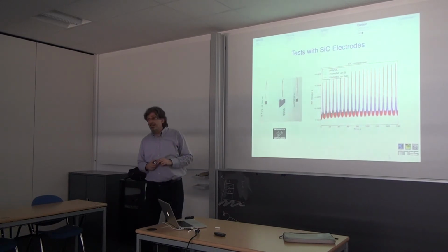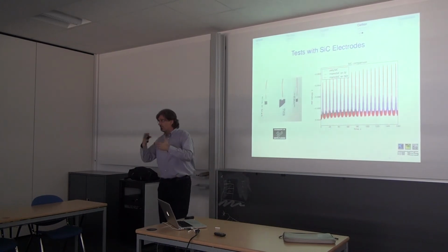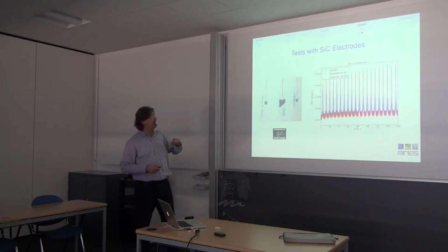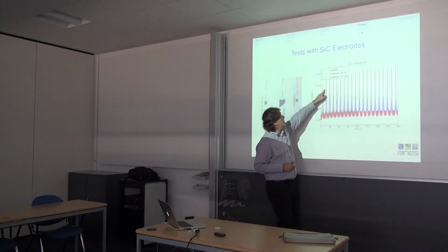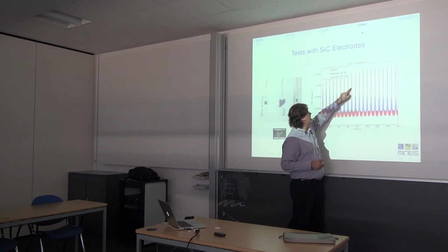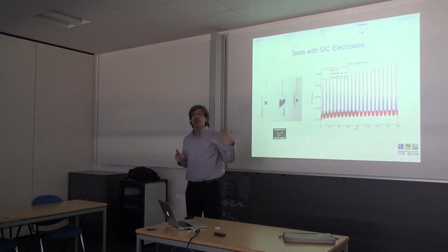From the other side, they gave us different types of polysilicon carbide, monosilicon carbide on silicon, and monosilicon carbide on SOI, so different possibilities. And we have seen that the efficiency of monosilicon carbide on silicon on insulator is better than the others, so we also did some preliminary tests.